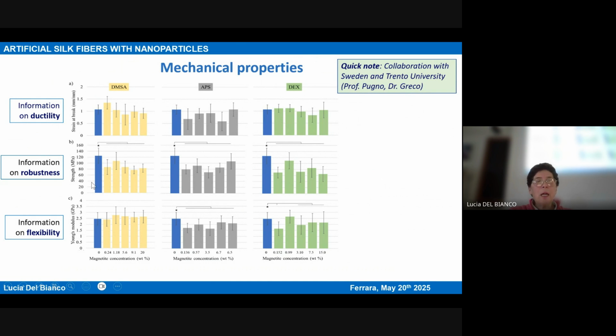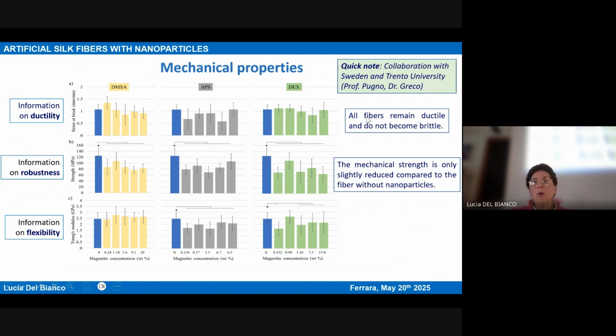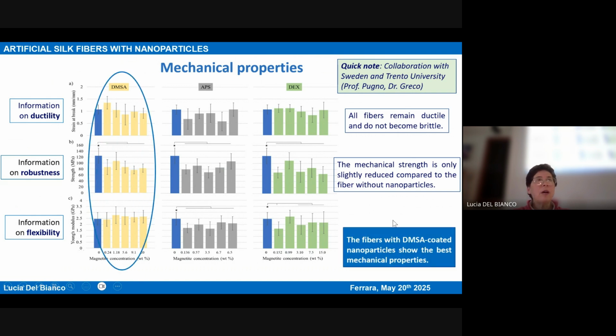And here the blue bars are the results for the fiber without nanoparticles, which actually is not as good as the natural one, but however is one of the best fibers produced by man. And therefore we observe that all the fibers remain ductile, do not become brittle. The mechanical strength is slightly reduced compared to the fiber without nanoparticles, but these are good results. Actually, the order of magnitude does not change. And as regards the flexibility, this set of fibers is the best one. So in general, the fiber with the DMSA coated nanoparticles shows the best mechanical properties besides the best magnetic properties.